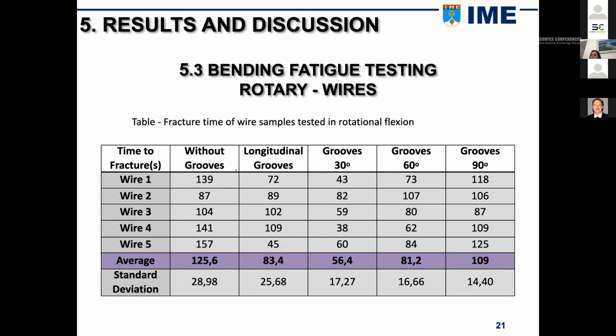This table shows the fracture time of the wire samples tested in the rotary bending test. As expected, the samples without grooves had the highest fatigue life, and samples with 90-degree grooves were expected to have a lower fatigue strength, as it was related to fracture mode 1, opening or traction, with cracks nucleated in the area of the greatest bending of the wire or instrument curvature. But the 90-degree grooved specimens had the second longest time to fracture.